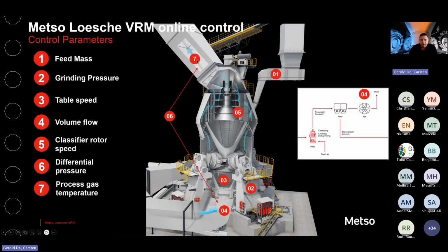If you have to dry, for example for gold roasting or nickel roasting processes, we observe the temperature to ensure that we don't utilize more heat than necessary, and therefore fuel and costs. And we also measure the product particle size. With the product particle size, we can use that signal to automate the control of the classifier RPM. Hence, if we see that your product is going out of spec, the system can control itself automatically.